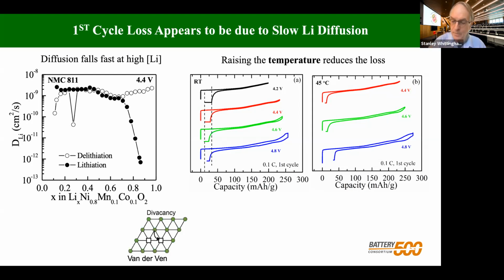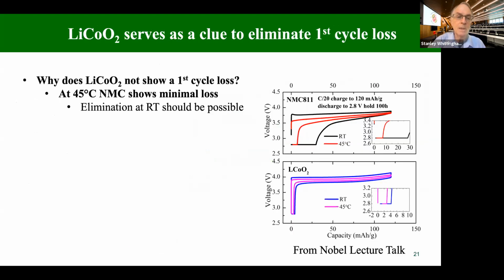So we were looking at how do we solve this, and there's several clues. One is cobalt oxide has essentially exactly the same structure. It does not show a first cycle loss. So let's look at these two plots on the right-hand side here. Here's the black curve. This is 80% nickel at room temperature. The red one is 80% nickel at 45 degrees centigrade with this constant voltage discharge. You can see both of these get back to the original position, and these were held for 100 hours. So again, this is saying kinetics is an issue here.